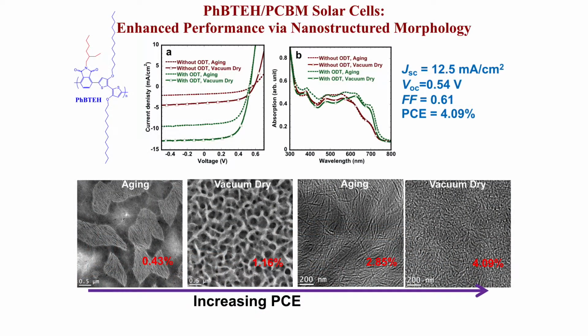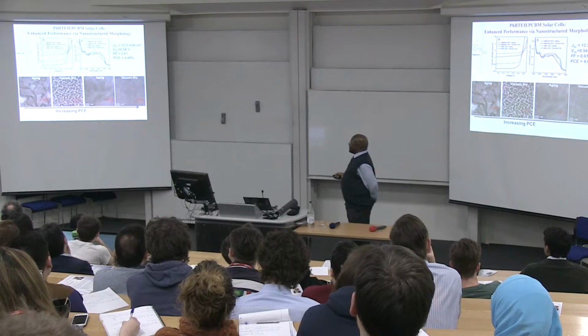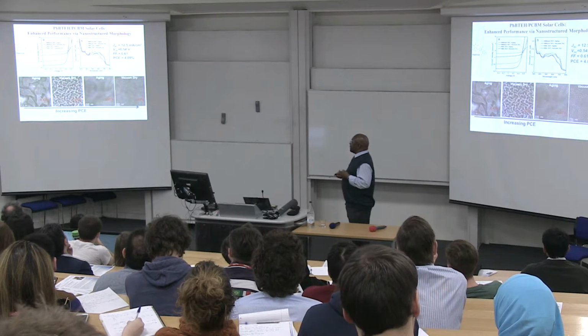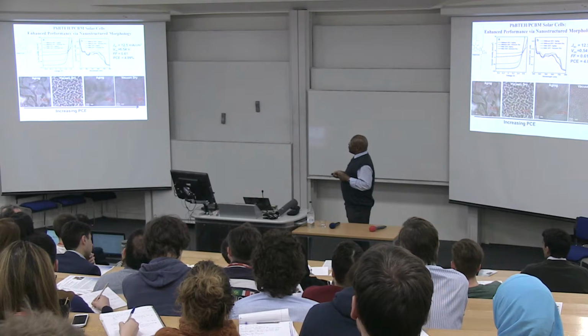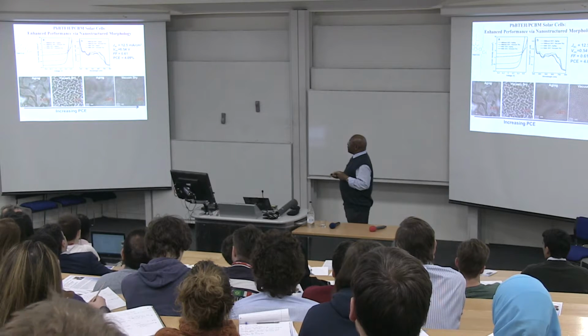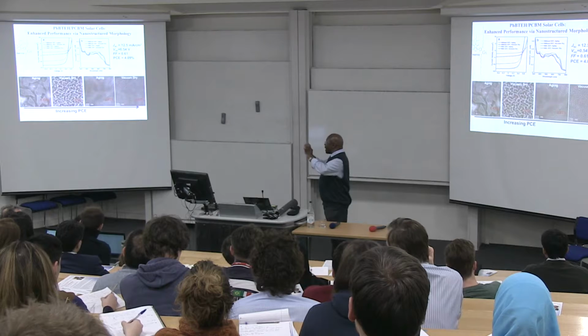So there are a number of approaches that have been taken. I have just two examples here. So one is to use different conditions to control the phase decomposition process, the drying of the solvent away from the film. And these, to varying degrees, can have some control, but what is shown here for this particular polymer using the PCBM that you have seen earlier is that if you simply spin coat a film and you leave it to dry at room temperature, this is the kind of structure that you have, very large domain sizes leading to very poor efficiency.